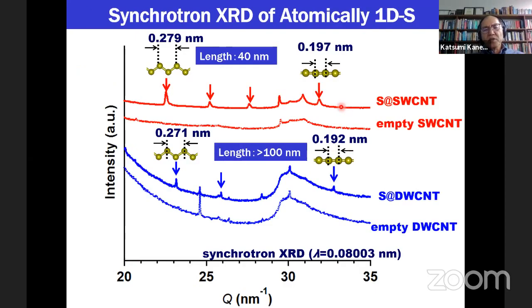This means the sulfur should be electrically conductive. And we can also observe synchrotron X-ray diffraction. For example, this comes from the completely linear chain in a single carbon nanotube. This peak corresponds to the sulfur-sulfur bonding distance. This is slightly larger than the bonding distance observed in sulfur compounds.